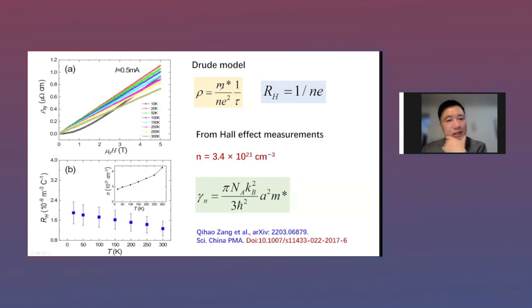But here we have two unknown parameters. One is the effective mass. Another one is the so-called charge carrier density, n. So we use the Hall effect measurement to get the Hall number, and from the Hall resistivity, we determine this charge carrier density. And also from specific heat, we can determine the so-called effective mass, okay?